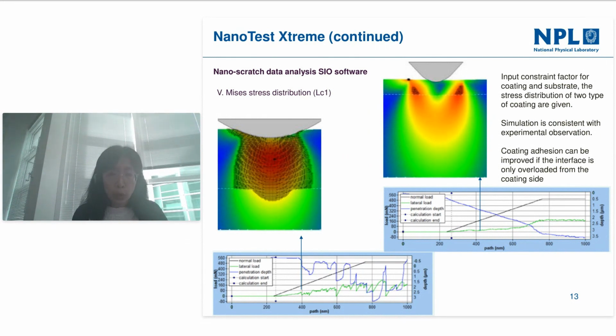These two coatings have similar modulus, but the coating on the left has a slightly lower hardness compared with the coating on the right. The arrow shows where the load was used to calculate the stress distribution. We can see the dark region in the coating and the substrate on the left side shows the plastic deformation, and on the right side the plastic deformation only occurred in the coating. So the simulation is consistent with experimental observation, and it indicates that to improve the coating adhesion,